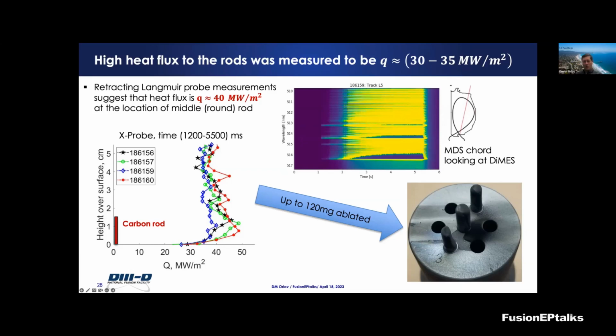When we measured those rods after the experiment—we did measurements both before and after—some of the rods lost up to 120 milligrams of ATJ carbon material.